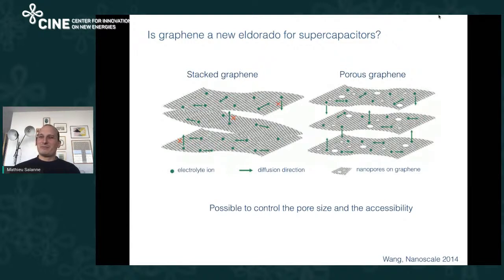a roundtable that we had at the International Society of Electrochemistry meeting 3 or 4 years ago, because everybody was ending their talks by, oh, now we will try graphene. And so we tried to see whether in simulations graphene was better or not. An important point is that to have a graphene material is not so easy because, of course, you can have some stacking problems that will limit the diffusion.